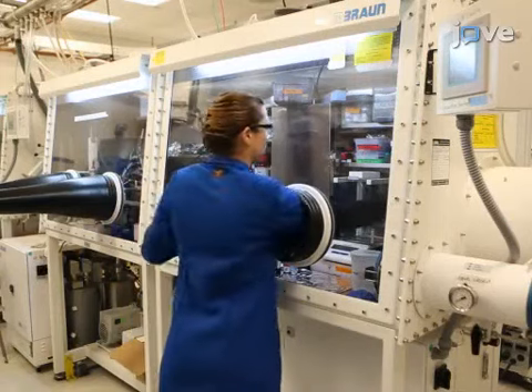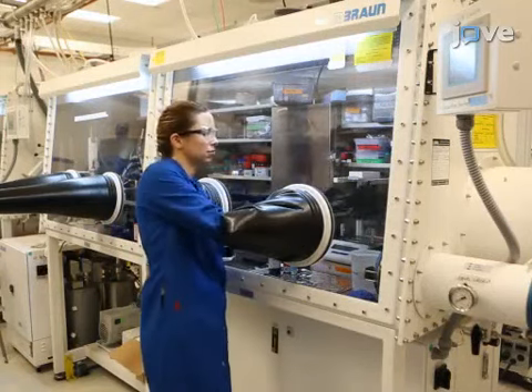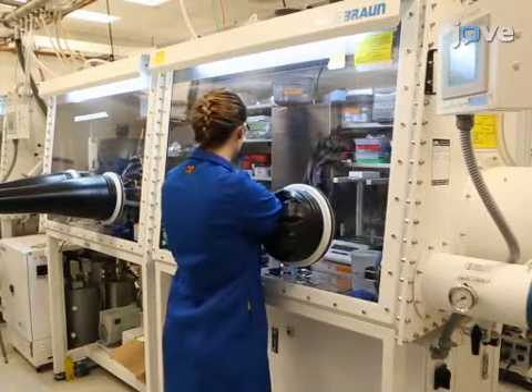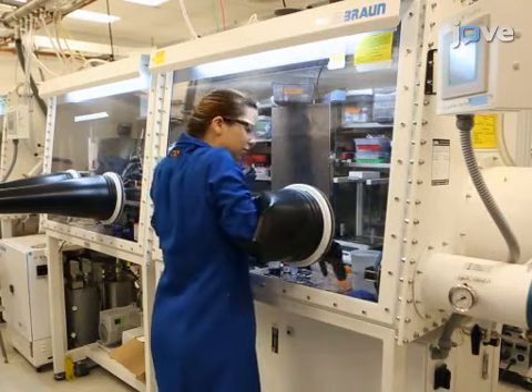Before beginning this procedure, synthesize polystyrene block polyethylene oxide copolymer, or SEO, using anionic polymerization as referenced in the text protocol. Perform all sample preparation in an argon glove box where the water and oxygen levels are controlled and remain less than 5 parts per million.